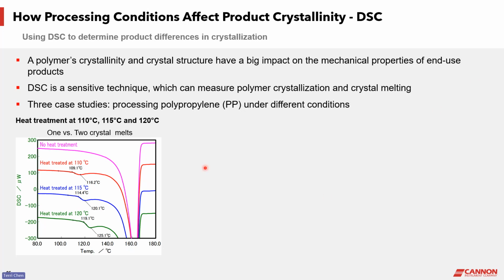The pink curve in this figure shows the melting of a regular polypropylene resin without any additional heat treatment. The red, blue, and green curves are the results of polypropylene resins that are treated at different temperatures, ranging from 110 to 120 degrees Celsius. From this DSC temperature scan measurement, we can clearly identify a second melting peak, which correlates to the melting of polyethylene. Therefore, we can conclude that this PP resin contains a small amount of PE, and with an additional post-processing heat treatment, the PE phase also gets crystallized.